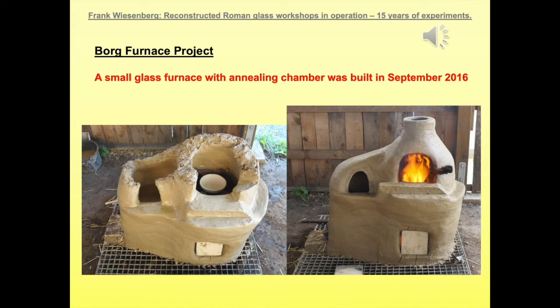The metal grid is just a solution to make this furnace movable inside the glass hot workshop, because the workshop was too small to have another furnace built there in situ, which could be left in place during the glass furnace research projects. After I did a test run of this glass furnace in September 2016, I noticed, even though I lacked the inspiration from the oil lamp at that time, that the layout I built just naturally included an adjacent annealing chamber close to the fire chamber and fire pit. I noticed that this design is much closer to the depiction on the oil lamp than the large furnaces we did before.